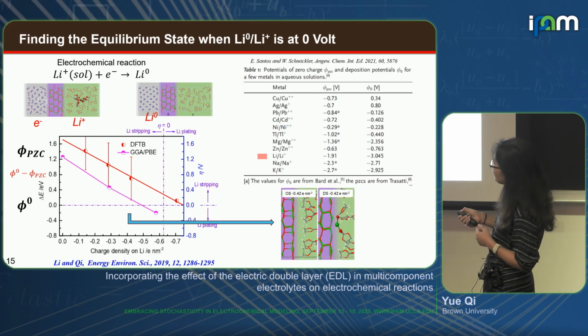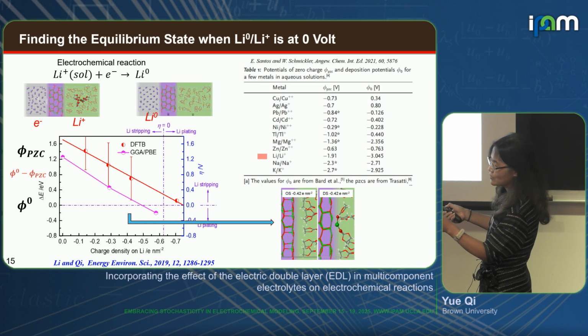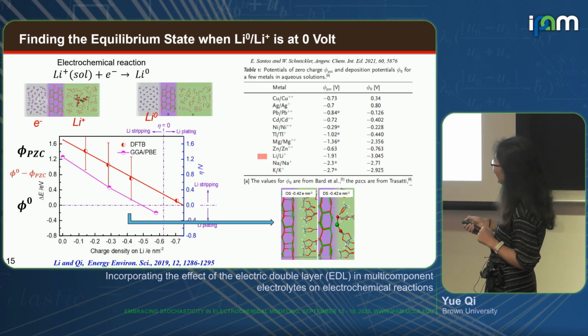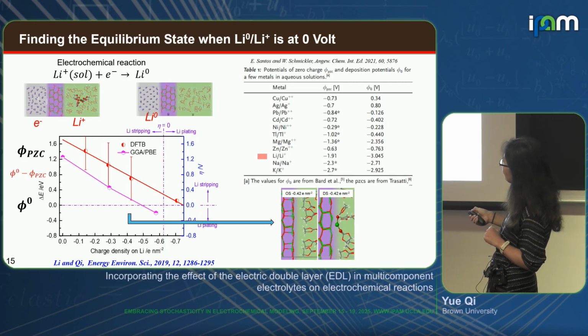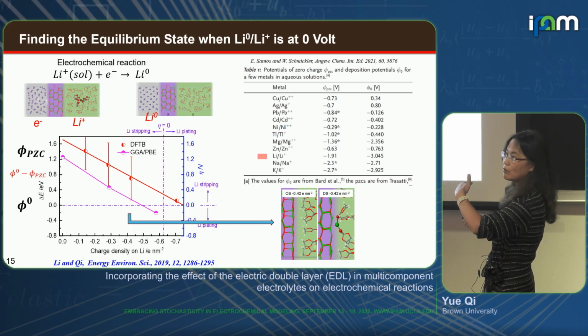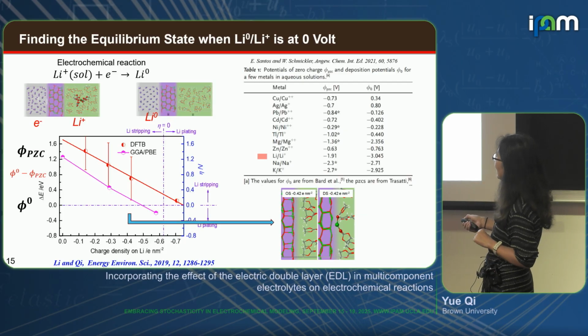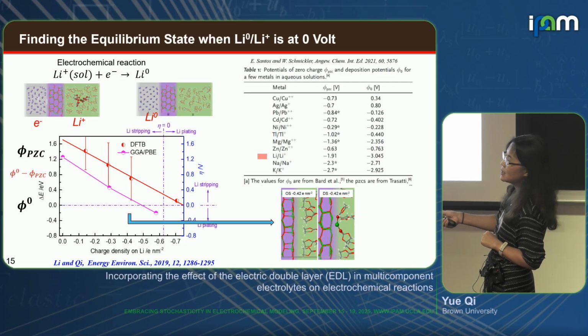When I did this work, I did the kinetics barrier for this. I'm not going to talk about that today, but when I did this work, we started to notice that when this lithium is charged, even though you have some passivation layer on the surface, these EC molecules have already reoriented, almost forming a strong dipole on the interface, and this is above the potential at which we deposit lithium, right?